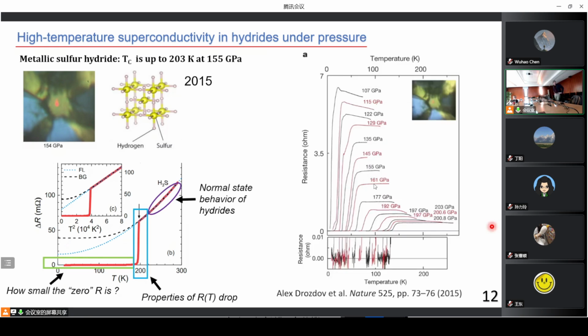This is one of the first experimental publications, made by Alexander Drozdov in 2015. It's a publication in Nature, and it's about sulfur hydride. We see that at high pressure in the normal state, the behavior of sulfur hydride is more or less normal. It corresponds to metals. This compound seems to have a positive temperature coefficient of resistance. So resistance, as expected, grows with temperature. Temperature increases and the phonons scatter the electrons, and the resistance also increases with this parameter.